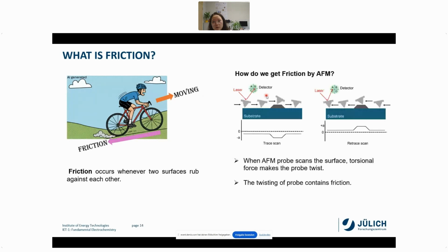Then how do we get friction by AFM? When the AFM probe scans the surface left to right or right to left, there is a torsional force applied to the AFM probe, and this makes the AFM probe twist. And the twisting of the probe contains the friction. Due to the laser location at the detector, the trace scan has a negative value of friction and the retrace scan has a positive value of friction. Therefore, we need both trace and retrace scans. If you are interested in how to evaluate the friction data, I can tell you later on.